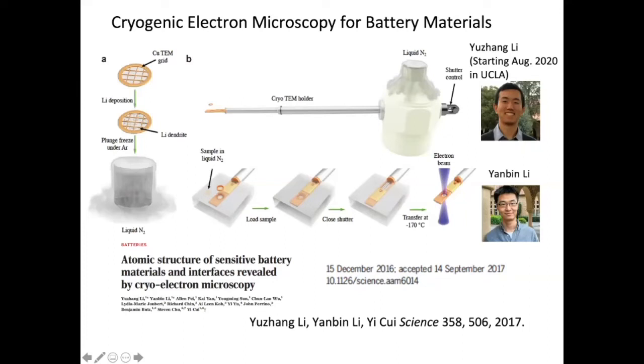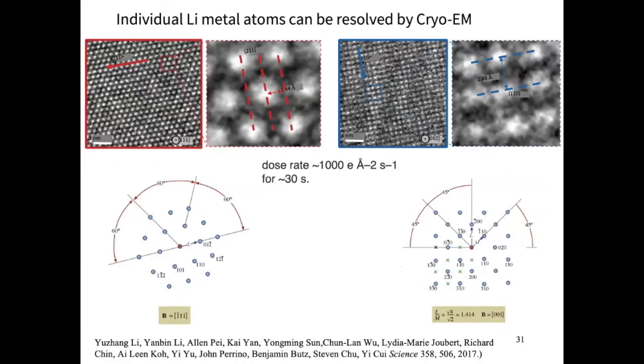And we are one of the earliest groups to adopt this technique. We developed lithium metal deposition and the plunge-freeze transfer without exposure to air, in a liquid nitrogen environment, into the TEM, stabilizing this lithium metal. We know lithium metal reacts with nitrogen. However, lithium metal does not react with liquid nitrogen. We can stabilize this lithium metal and start to do imaging on these materials. We were able to see atomic scale resolution of metallic lithium. I think this is for the first time.